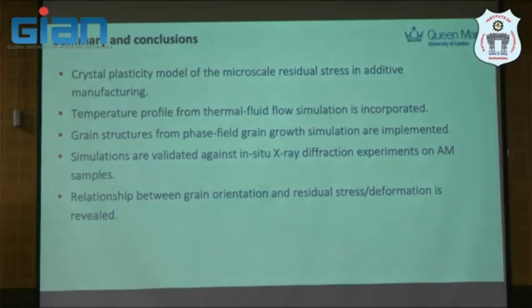So, to summarize this section on the crystal plasticity model: in the micro scale, a crystal plasticity model has been implemented for micro scale residual stress in additive manufacturing. The temperature profile is actually used from thermofluid simulation. Okay, it's coupled now, so you see how things transfer across. Grain growth is predicted with phase field grain growth, which is also coupled with the thermal fluid. This simulation is validated again with in situ X-ray diffraction on an AM sample. And this relation between grain orientation and residual plastic deformation is revealed, which was not seen like this before, right? With experiment it's probably hard, but here you basically get the time resolved residual stress profile from modeling.